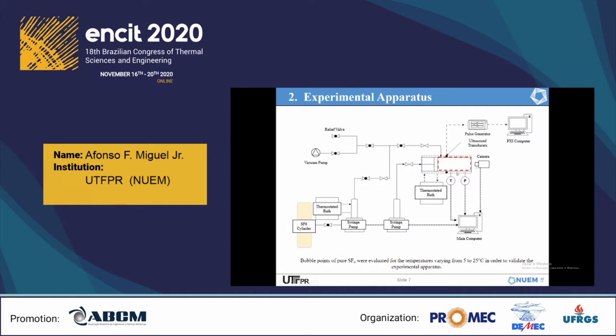For ultrasonic measurements of the phase change, an acoustic signal is provided by a pulse generator and fed into the cell via a contact ultrasonic transducer of 1 MHz. A second identical transducer monitors the signal at the other side of the cell. The resulting signal is amplified and displayed on a PXI computer. Temperatures were measured using an RTD-PT100 directly and intrusively in contact with the mixture. Pressure measurements were carried out using a pressure transducer connected to the interior of the cell. An endoscope camera was used to illuminate and capture images of the mixture inside the cell.